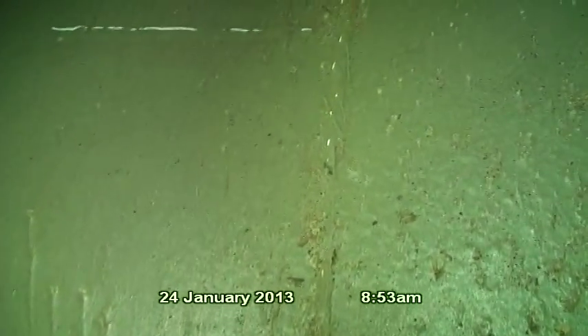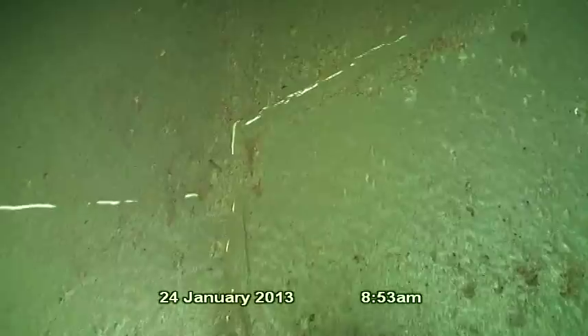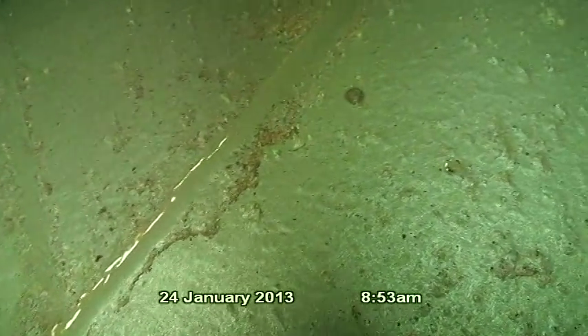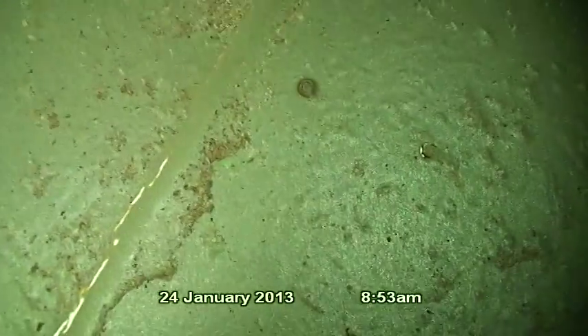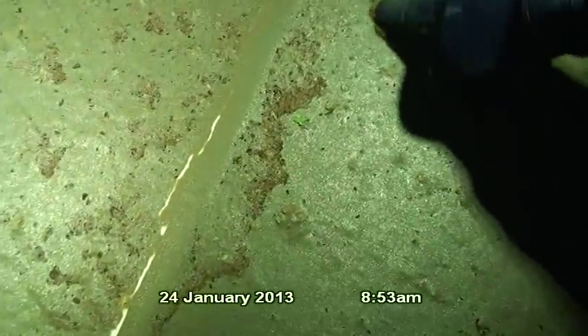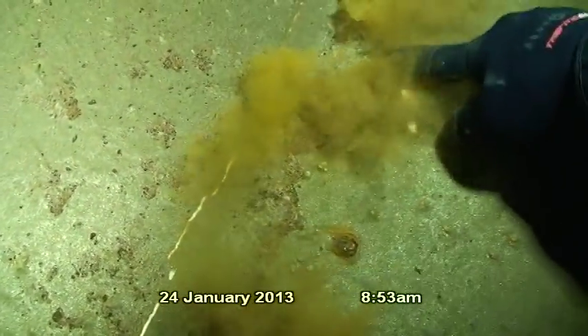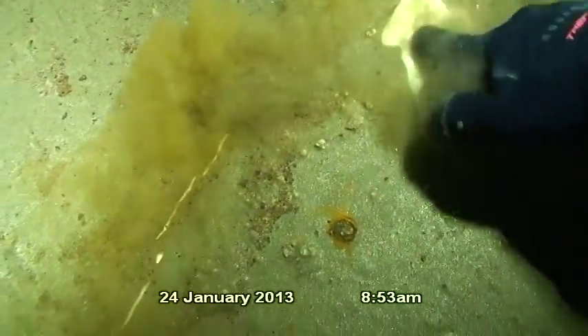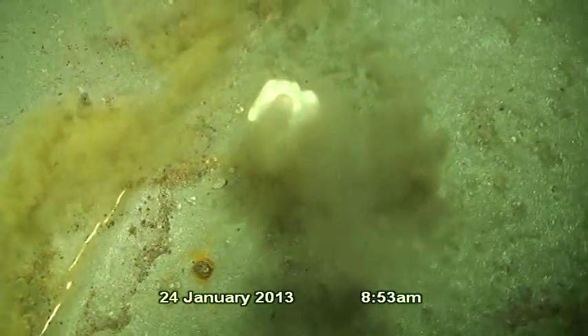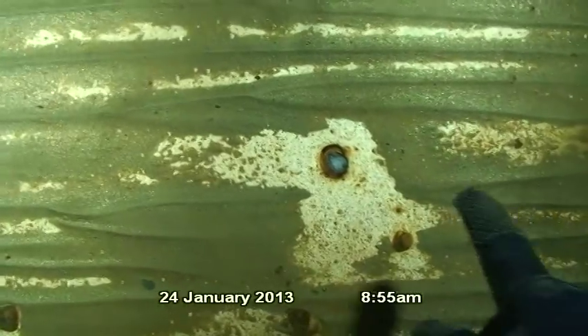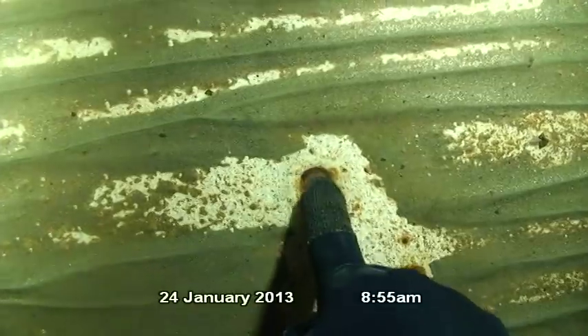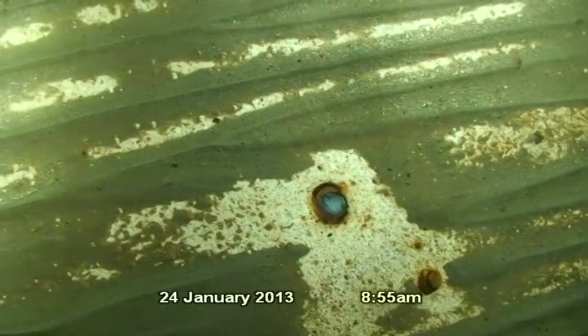We've now returned to the floor, which is covered with sediment at this time. At the conclusion of the wet inspection, all of the loose sediment and debris will be removed from the interior of the facility. Here, a corrosion nodule is visible through the sediment. The diver inspector has removed the corrosion nodule in this area, and slight metal loss is taking place in this location.